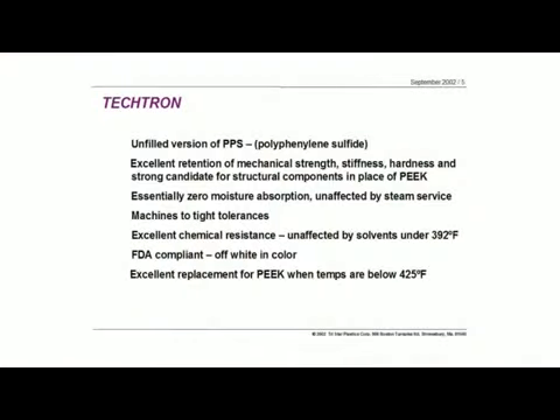Even though that's the trade name, Techtron is also the unfilled version of this family. Most of the PPS that you see on the market is usually going to have some kind of a filler. There's a lot of the Ryton product out there, or Fortron, where glass fibers, carbon fibers, and other fillers are used, and that's primarily because it's historically a difficult material to process in some ways. But the Techtron material, being a virgin material, allows for a lot of interesting applications, and one of those is that it is FDA compliant. If you have glass and carbon fillers in it, you won't have that compliancy.